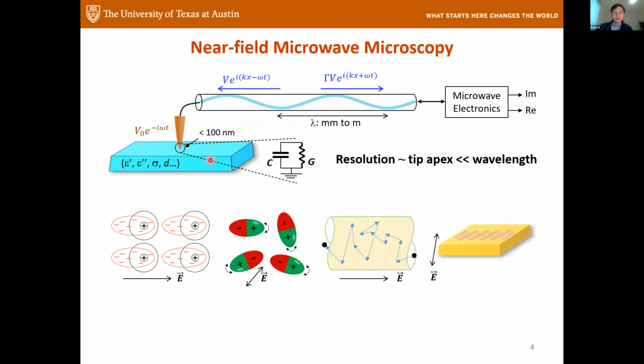And I would say 80% of my work is on conductivity. So this particular work shows imaging of this complex oxide down to just 2 degrees Kelvin. And there's a phase transition within this around 114 degrees Kelvin. And you see during the phase transition, there's this stripe phase, which is much more conductive than the background. And the last one was actually, again, a surprise to us.